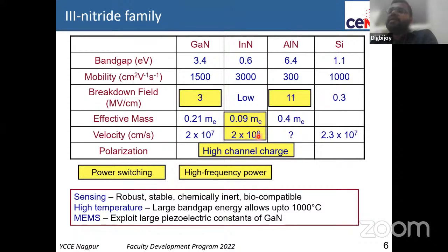Okay. Similarly, you can see that mobility is very high, electron velocity is quite high, you can get very high charge, and all this enables gallium nitride devices which can carry higher current and still block higher voltages than silicon. Makes it very, very attractive for high power switching, high frequency radio wave device, radio frequency devices, and so on. And because this is a very wide bandgap material, you can go to much higher temperature and still be okay.